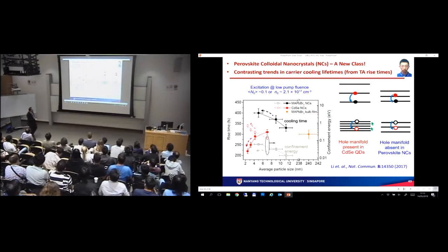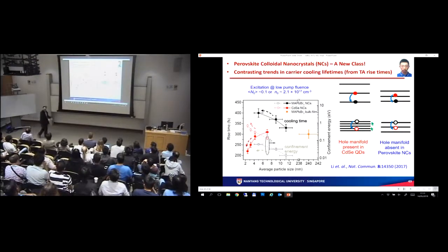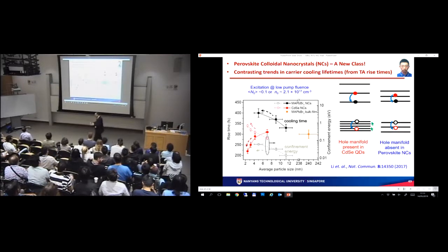Now, if you compare that with cadmium selenide quantum dots, which we did as a control experiment, as you shrink the particles down, your rise time goes faster. That is a signature that the phonon bottleneck is breached. So you can't really make use of the phonon bottleneck in your traditional cadmium selenide quantum dots. So we have a very contrasting, new class of nanoparticles which we can use to preserve and keep the bottleneck intact. One of the key reasons why this bottleneck is absent in cadmium selenide, unlike your perovskite, is that you have a hole manifold because of the hybridization effects, and that gives you very closely spaced levels. If you think about it, if you lose either the hot electron or the hot hole, then the whole concept fails, and whatever bottleneck effect you are trying to preserve is gone.